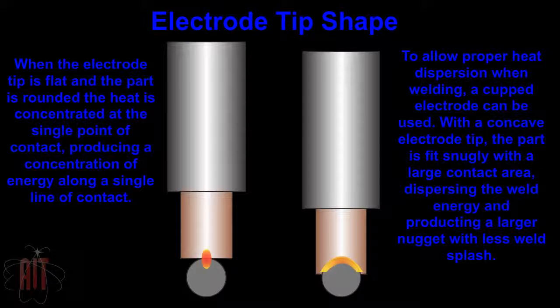When the electrode tip is flat and the part is rounded, the heat is concentrated at the single point of contact, producing a concentration of energy along a single line of contact. To allow proper heat dispersion when welding, a cupped electrode can be used. With a concave electrode, the part is fit snugly with a large contact area, dispersing the weld energy and producing a larger nugget with less weld splash.